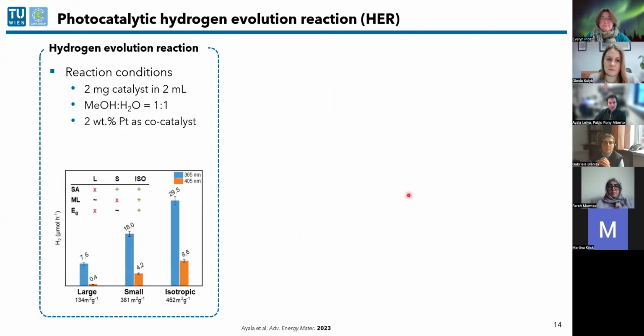Good, and now to the experiments. So these were our reaction conditions. We use a methanol water mixture, methanol here acting as a sacrificial agent or a hole scavenger. And we also add platinum nanoparticles as co-catalysts to exchange the charges. And here you see the results of all the particles that were investigated.